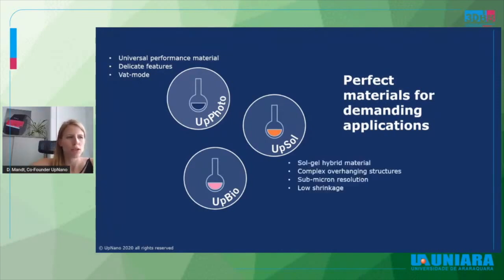The UpSol is a sol-gel hybrid material consisting of organic and inorganic components. Here we can structure very complex overhanging structures, for example, because this material is gel-like at room temperature. So the material is prepared, then the ethanol or the alcohol is evaporated, and then you have a gel-like material where you can print in. And this gel serves as a supporting structure of the structure you're printing. So therefore, very complex overhanging structures, but also structures above each other. So a layer of structures and some material in between and another layer can be produced using this material. Here you can also achieve very fine structures, so sub-micrometer resolution is definitely feasible. And the material characterization is also that it has a very low shrinkage rate.